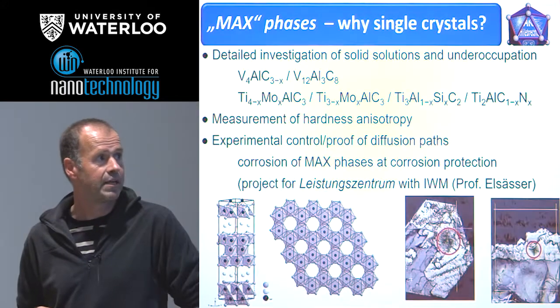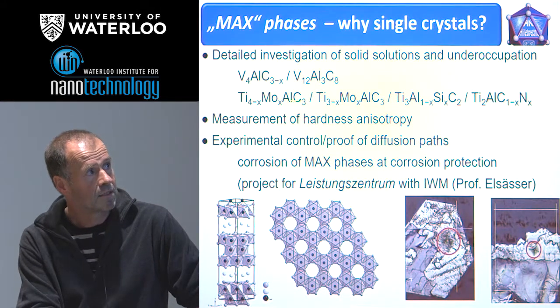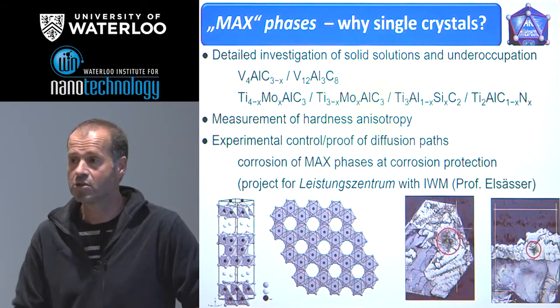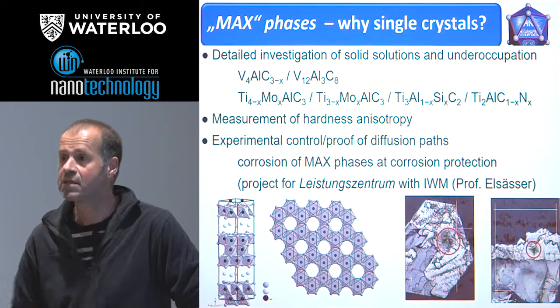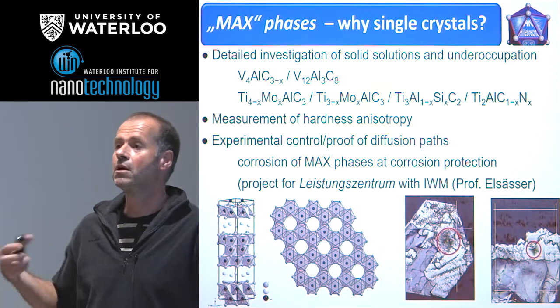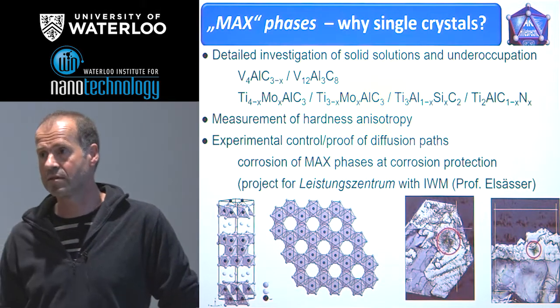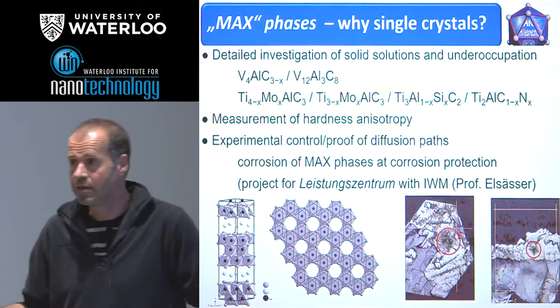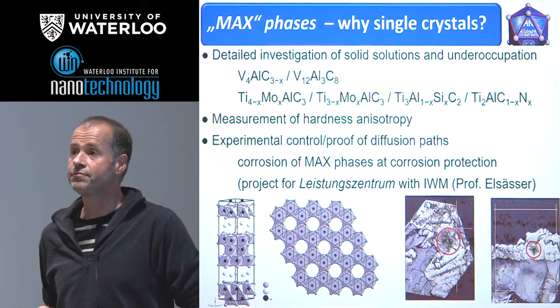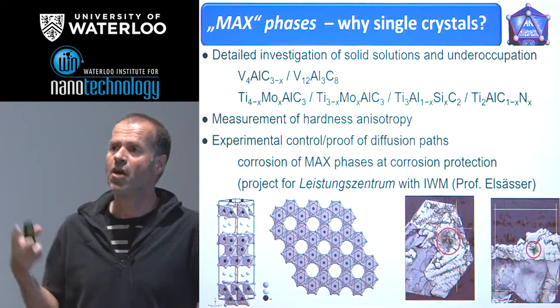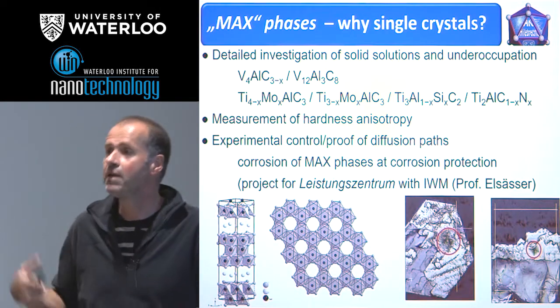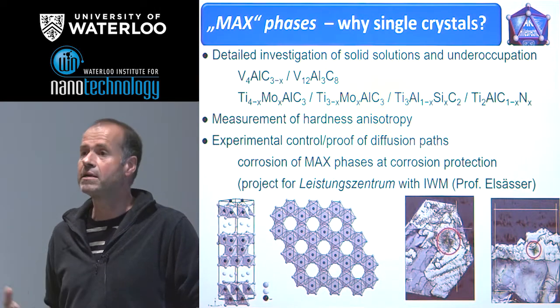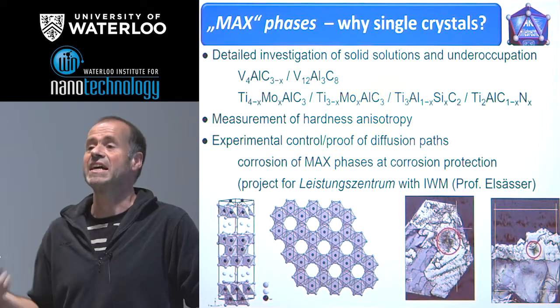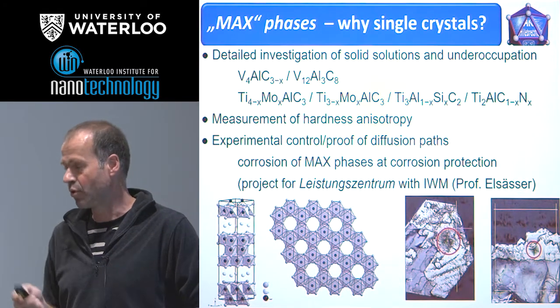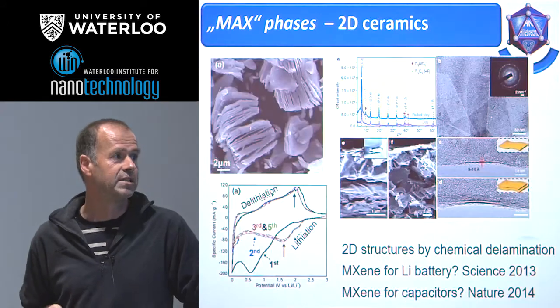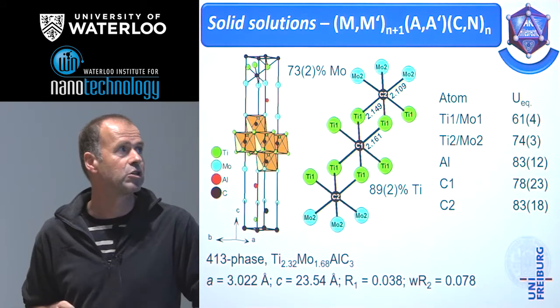And then it becomes again important how we can substitute these transition metals, the main group elements, because we have an influence on the delamination process according to the reactivity from the deintercalation. And we have an influence on the properties of the remaining transition metal carbide or transition metal carbide nitride layers. And that's why we guess it's important to investigate it in more detail. And some of these details I will show here.